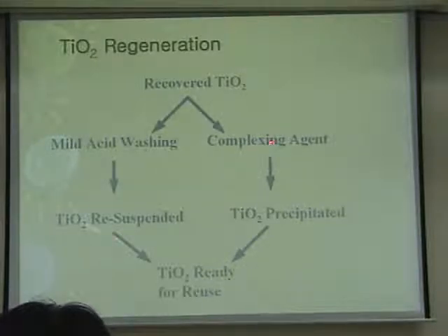The next method was using complexing agents, simple complexing agents. When we adopt this complexing agent, it works much better for ferrous compounds than for ferric. So we have to introduce another step here to convert the ferric into ferrous by simple boiling and using ascorbic acid or hydroxylamine hydrochloride. We have to convert the ferric into ferrous, which then the complexing agent can capture the ferrous ion metal